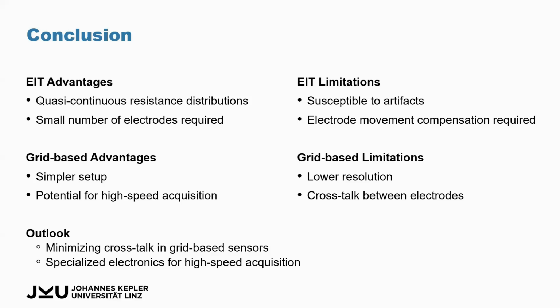For the grid-based, that's where it has some advantages. We're not making any assumptions about the system, so we don't have to do reconstruction. So it's basically a simpler setup. And if we go into, for example, the zero potential circuit method, we can get to lower crosstalk and also very, very fast measurement cycles, which is important for the dynamic phenomena we're trying to capture here. The disadvantage is that we get a lower resolution, but that depends on the number of electrodes, basically. And we have to eliminate the crosstalk.